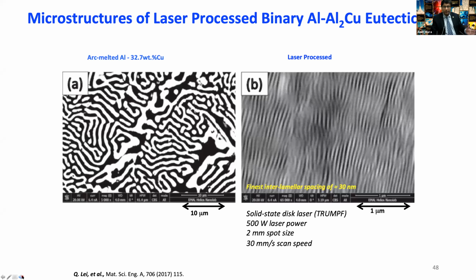Similar behavior seen in the other eutectic of aluminum to copper, where this is more surprising because aluminum to copper is a tetragonal structure. Tetragonal is not cubic. Silicon at least is cubic.